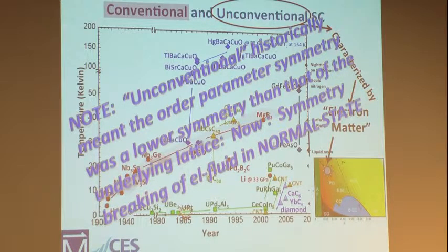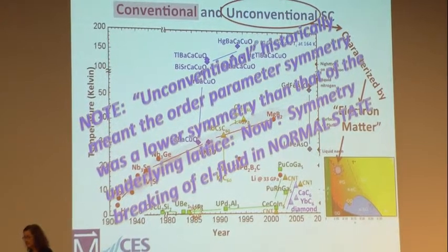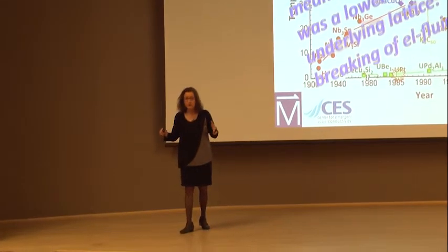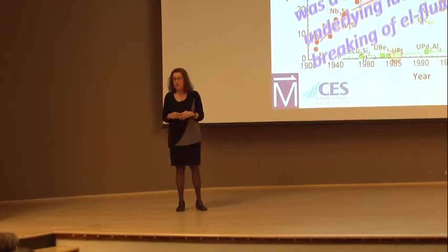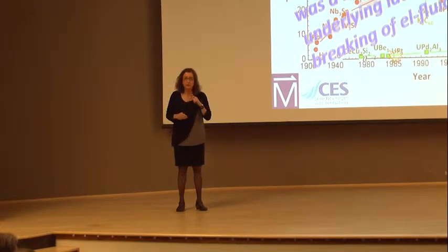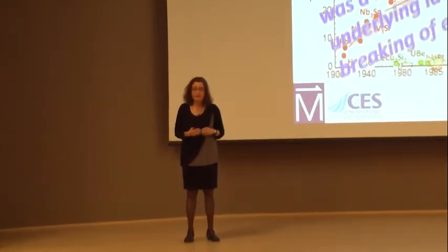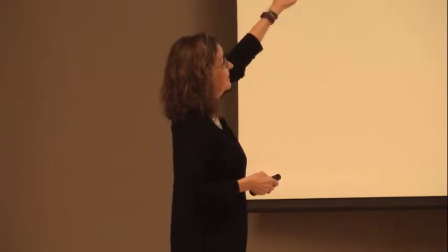But the iron-based superconductors are probably not D-wave. They're probably something we call S plus minus, which is basically S-wave, which is basically the same symmetry as the underlying lattice. But I believe they're still unconventional. They still have the same phase diagram. And what we find, and I'll spend a little bit of time talking about it, is that the electron fluid above TC breaks the symmetry of the underlying lattice. So, okay, I'm going to show you that. I'm not kidding you. Conventional, I'm just reiterating because I like my definition up on my soapbox.